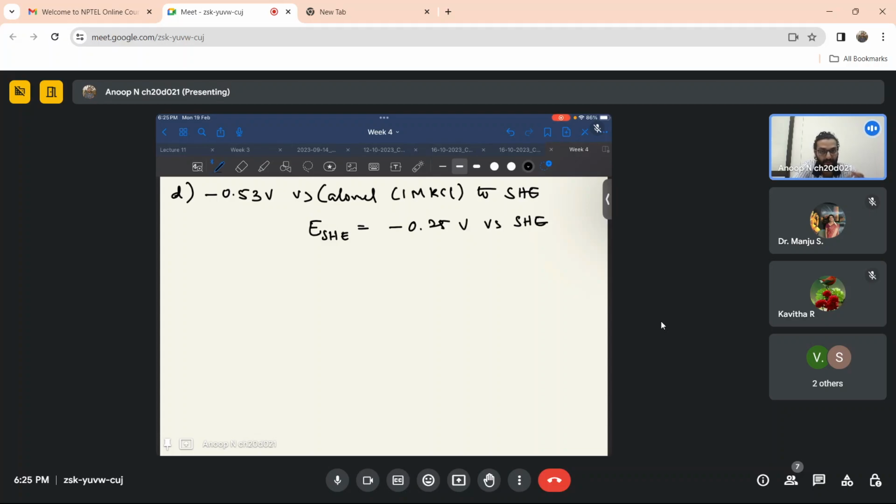Why I'm emphasizing this is, when you are using Ag/AgCl or standard calomel or saturated calomel or other calomel electrodes, the potential depends upon the concentration of the KCl filling. So make sure when you convert the values, you are taking the correct value, and that you are taking the solution concentration accurately. Even when you buy it commercially, you may be filling the KCl solution in it, because the KCl concentration tends to increase as the liquid evaporates and the KCl crystallizes.